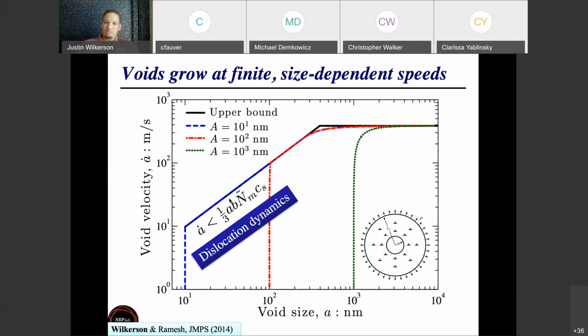they're able to grow even faster, which again adds to that instability. Micron-sized voids, the situation is a little different. Their kinetics are actually governed by that inertial resistance that we talked about earlier. So the fact that as you grow these voids, you have to accelerate mass out of the way, that becomes the primary constraint for the dynamics of micron-sized voids. Okay, and then we have a simple kinetics law that governs that.